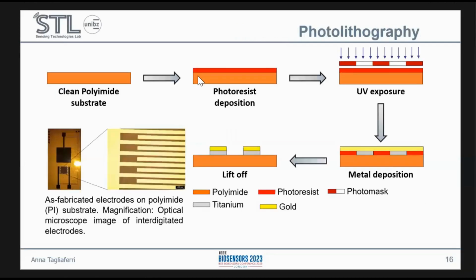First, I started with the fabrication using standard negative photolithography. I chose a polyimide substrate, a flexible substrate. I deposited the photoresist by means of spin coating, exposed it to UV light through a patterned mask. I then deposited an adhesive layer of titanium using electron beam, followed by the thermal evaporation of gold. After 1 hour liftoff in acetone, these are the devices that I ended up with.